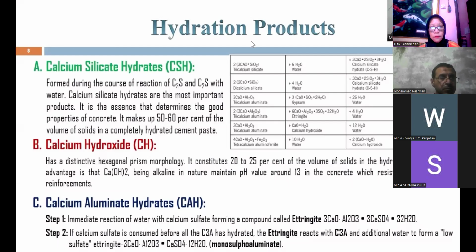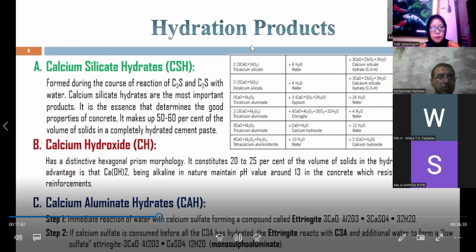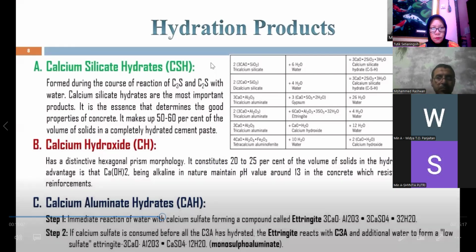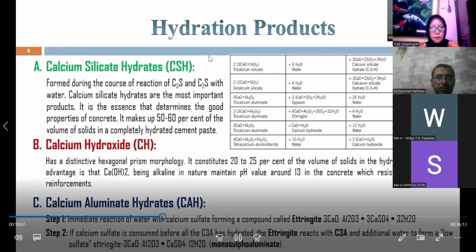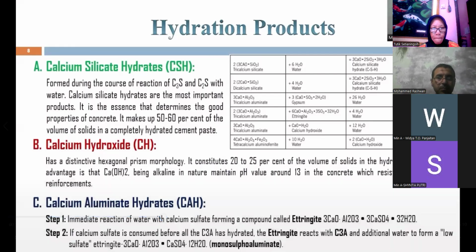The last hydration product is calcium aluminate hydrate. This product occurs during two reaction steps. The first reaction step occurs between C3A, water, and calcium sulfate. The source of calcium sulfate is gypsum or another source of sulfate. Calcium sulfate from gypsum reacts with the C3A phase and water, forming the most famous product, ettringite, calcium aluminate sulfate with a high amount of water, 32 moles of water.